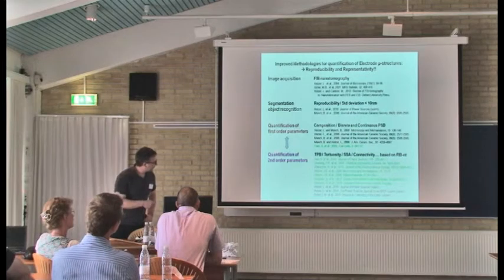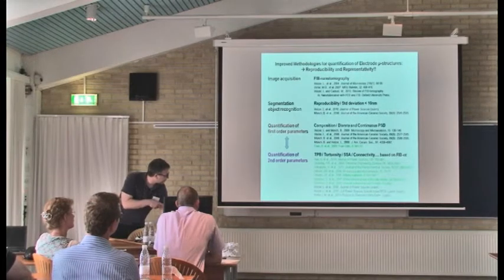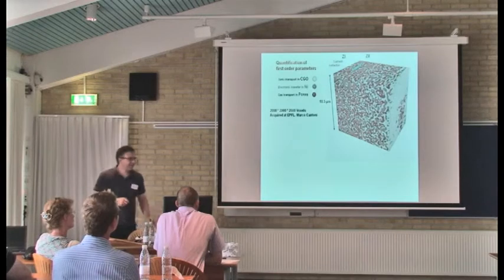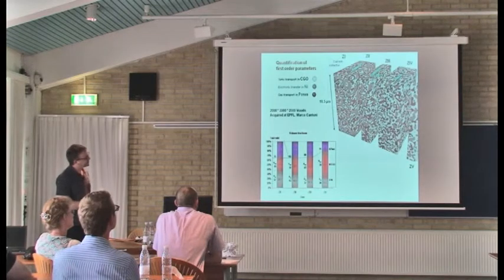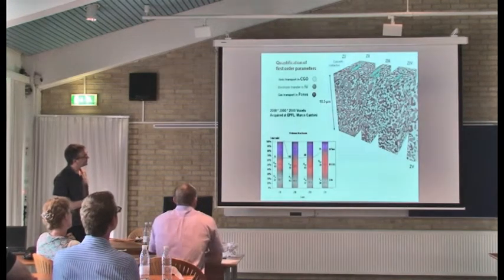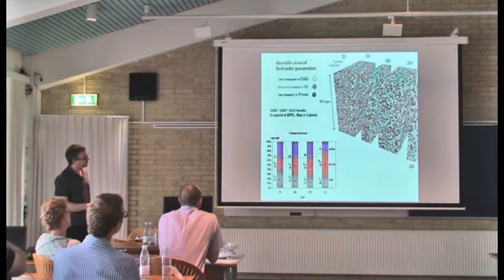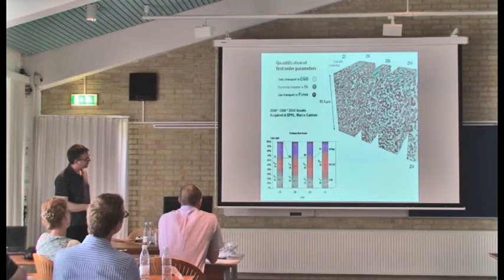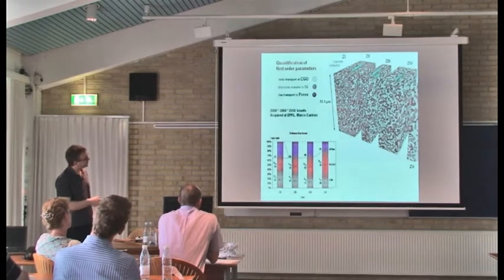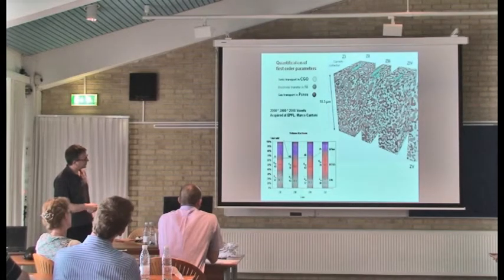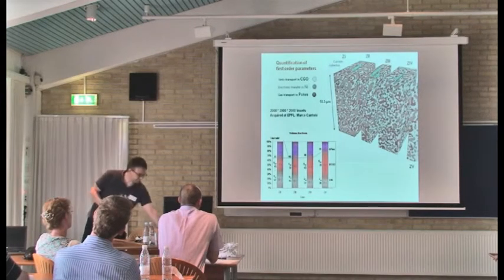We can apply this to FIB tomography data. This is a cube with about 2,000 slices and it has a graded microstructure. We have four zones. First of all, the composition. You see how the nickel increases from over here, which is the electrode-electrolyte interface. Here's the current collector. Nickel is increasing in this direction, and in the same direction CGO is decreasing.